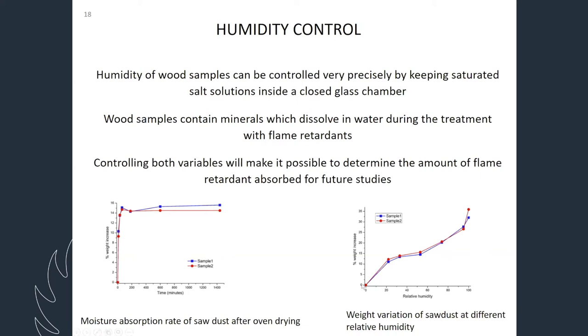So now the dried wood we kept at different humidity chamber conditions, and you can see humidity slowly increases. And it can even increase 35% when we keep 100% relative humidity, which you can achieve by keeping just plain water inside the chamber. So that is our basic understanding when we prepare samples in the future, how much moisture content it originally had. Because now what happened, now I can tell you, when we take, say, 1 gram